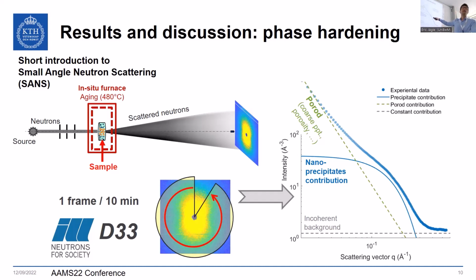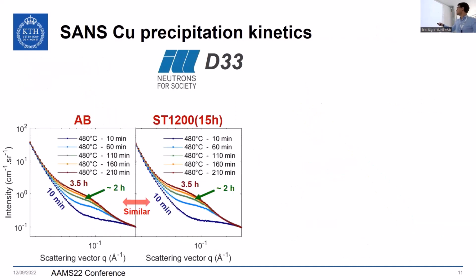And we have this nano precipitate contribution, which made this kind of bulge, which is the one that's interesting the most, right? So let's see how this contribution moves with the aging time. Here I put the two extreme materials, the as-built material and the solution treatment material at the highest temperature. And you see the scattering pattern after 10 minutes, 2 hours, up to 3.5 hours.